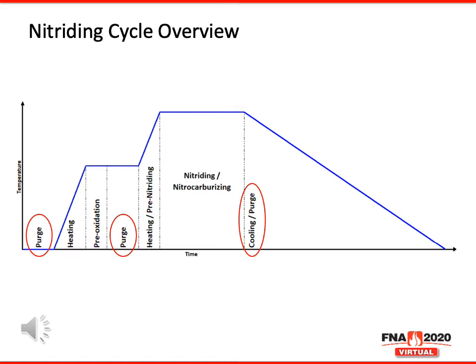As I mentioned, there's not typically a whole lot that can be done to achieve meaningful time savings from a nitriding step. You're limited by the diffusion of nitrogen into steel and the rate at which that occurs. There could be a little bit that could be done to speed up the heating rate depending on the size of the heating system on the furnace. But again, you do have to be aware, if you heat too fast, you'll heat the outside of the load up to your desired temperature, but the inside of the load will still lag behind, and you may need to wait while you're at temperature for the rest of the load to be uniform prior to nitriding. So again, there's kind of limited options there.